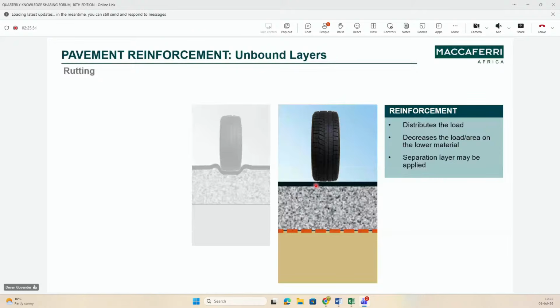So some examples for you showing unbound layers. You can see here the placement of your grid. When we start talking about reinforcement as a separation geotextile, essentially, when we're looking at our pavement layer work, this is our subgrade and we're coming to put in our layer works in there. If we're putting in a granular base, with no geotextile on the left-hand side and with geotextile on the right-hand side, on the left-hand side without geotextile, what's going to happen is our granular material is going to be lost into our soft substrate.